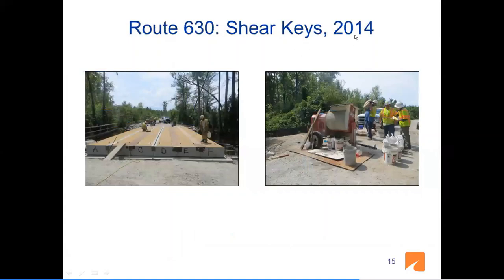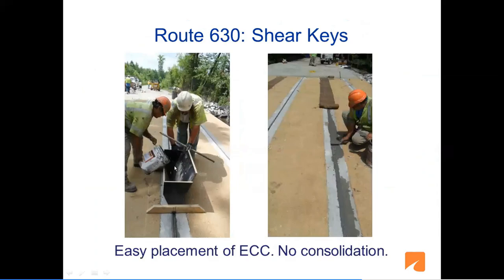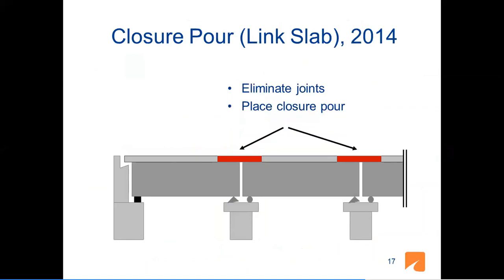And then we went to another bridge the following year, 2014, as you see here. We put ECC on all these shear keys. You see that there are 1, 2, 3, 4, 5, 6 shear keys. On site, in this mortar mixer, as you see, they had batched up dry materials, mixed it in this mortar mixer, and then again used the trough I had and placed it in buckets, poured it into these shear keys. And then they are finishing it. There is no consolidation, easy placement. And then they put this burlap to cure it, wet burlap on top of it. So that went very well too. So now we have a special provision in Virginia that we are using, ECC in shear keys.